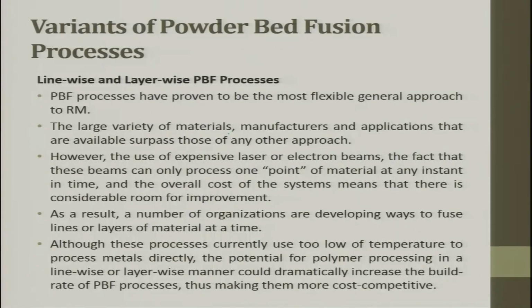The large variety of materials, manufacturers and applications that are available surpasses those of any other approach, powder bed. However, the use of an expensive laser or electron beam, the fact that the beam can only process one point of the material at any instant of time, and the overall cost of the system mean that there is considerable room for improvement. Why? Because the laser goes spot by spot, EBM also goes spot by spot. So now instead of going spot by spot, if I can put a small mask and allow light to fall, the entire thing is done as one line in one shot with very high resolution.